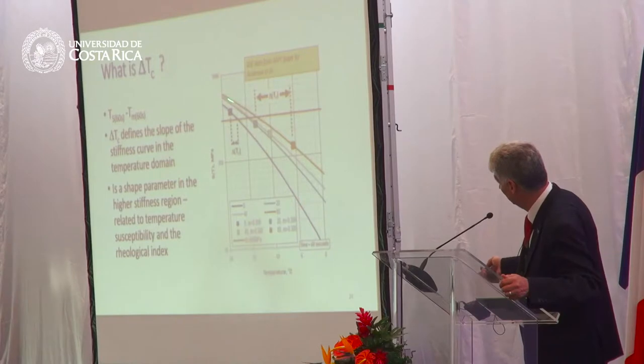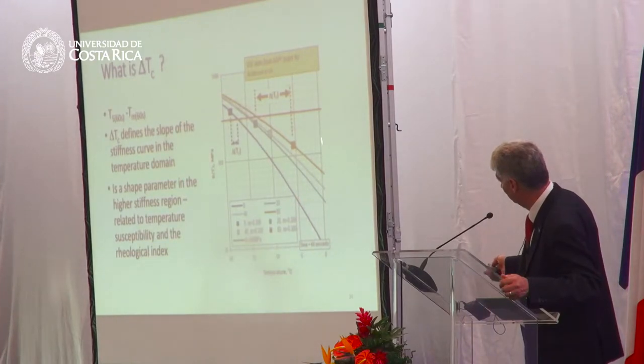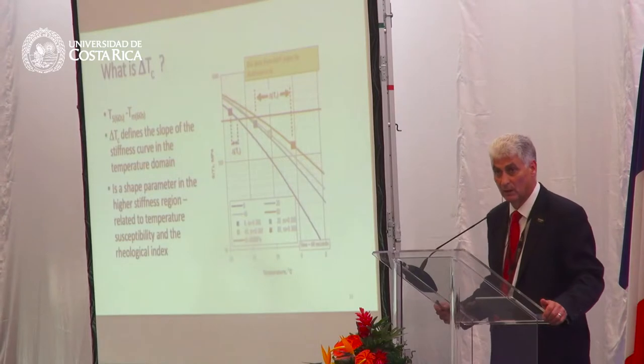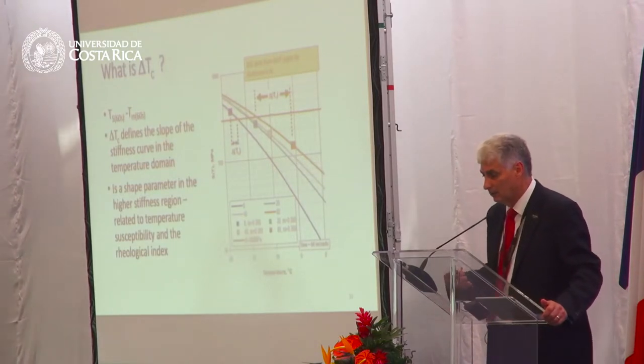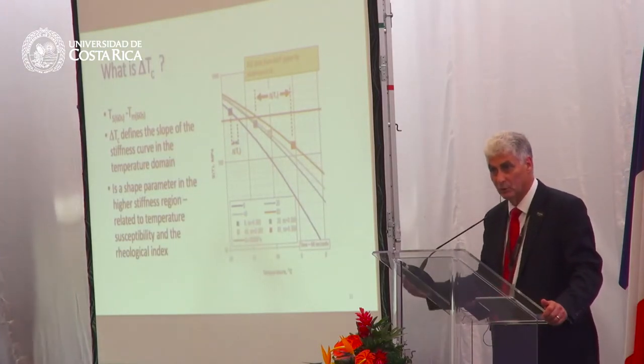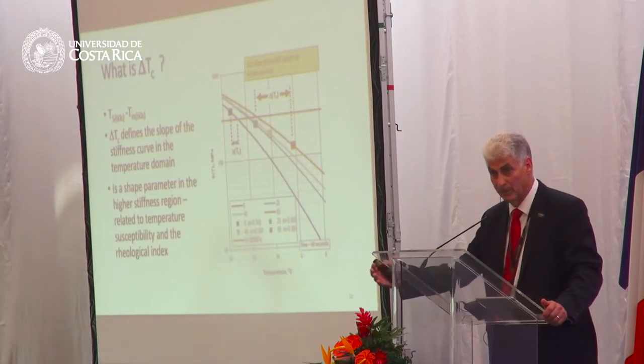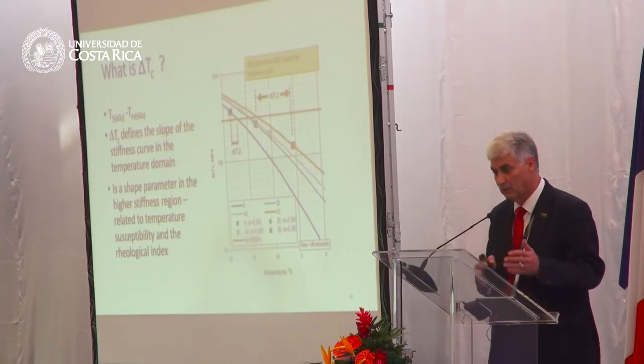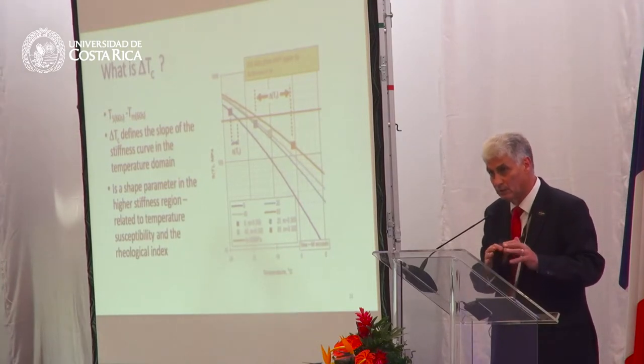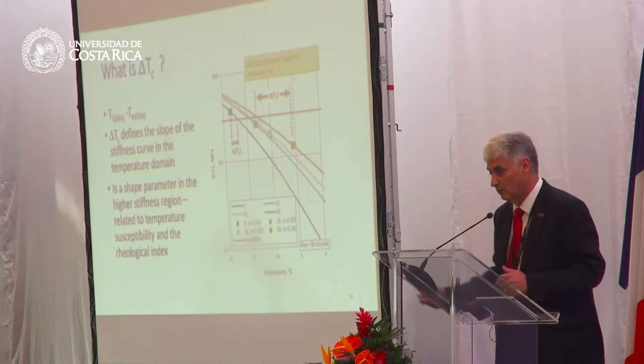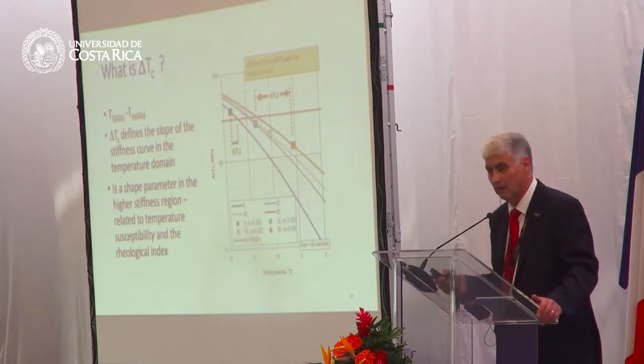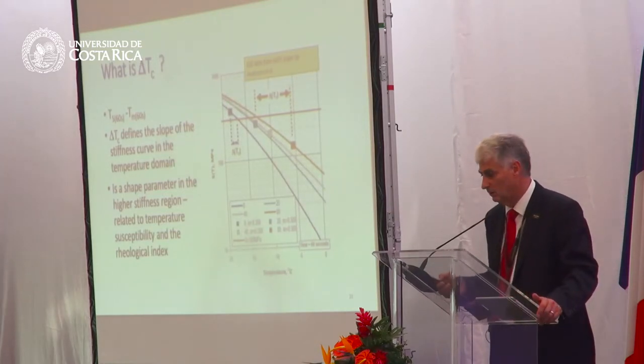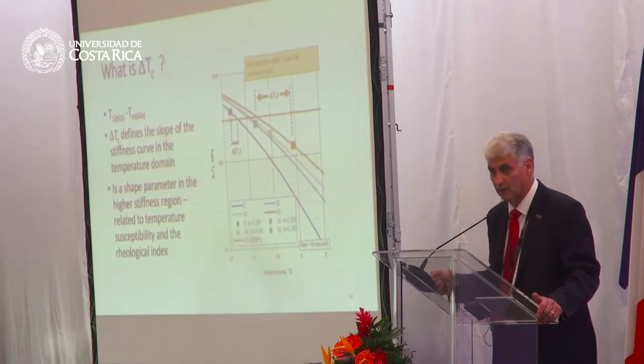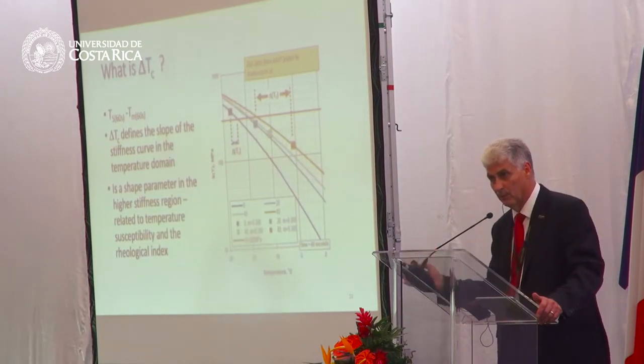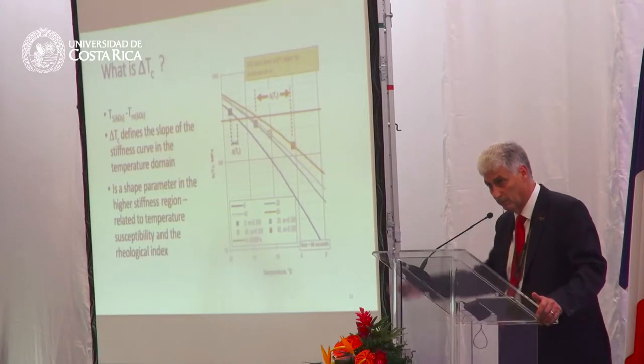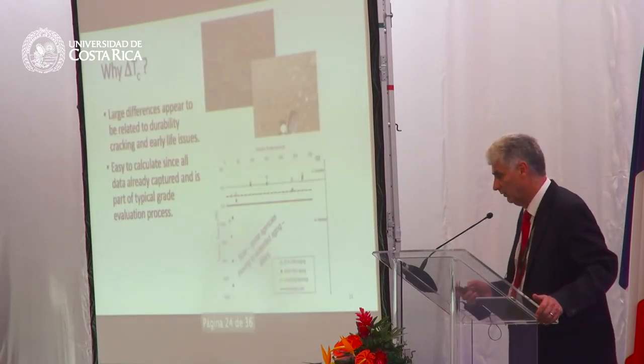So in this case, the delta TC is a small positive value. In this case, the delta TC is a reasonably large negative value. And it's a shape parameter. As materials oxidize, the delta TC becomes more negative. Sometimes it starts as a small positive value, sometimes a small negative value, and as the material oxidizes, it gets to be more negative. Ideally, we do not want a delta TC which is going to be over something like about minus 5. So we want it to be minus 5 and above rather than minus 5 and below. So that's sort of the limit on that.